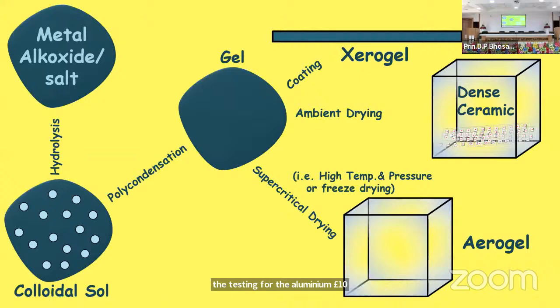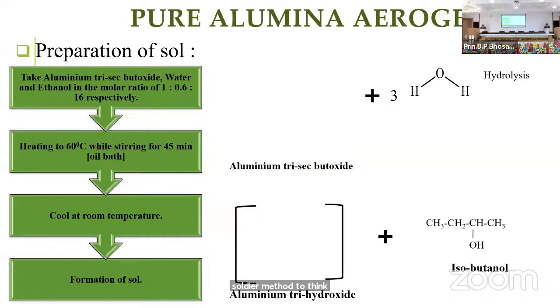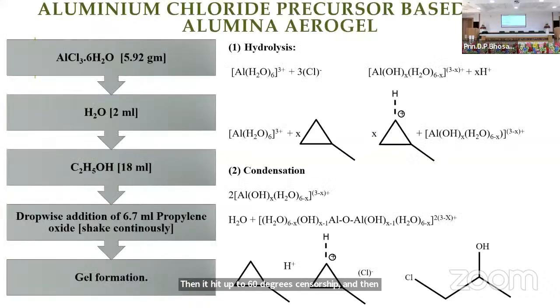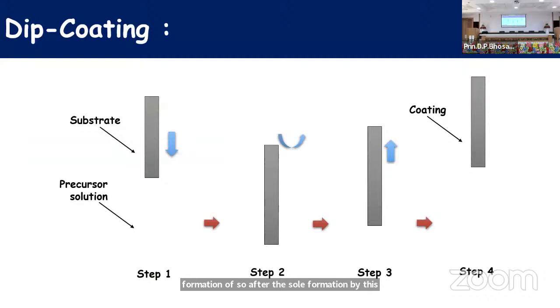So there is a basic way of forming a thin film by the Sol-Gel method. There is a chemical reaction of aluminum thin film formation. Here we use the aluminum precursor, that is aluminum tri-sec-butoxide, and it acts as a precursor. The molar ratio is 1:0.6:16. That ratio is aluminum tri-sec-butoxide, water, and ethanol. Then it is heated up to 60 degrees Celsius, and then the sol forms. After the sol formation, by this technique, we use a dip coating unit for coating the thin film.